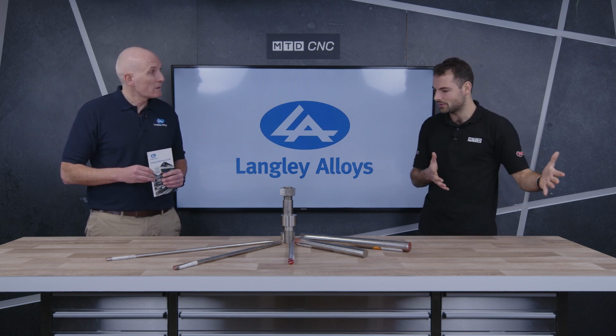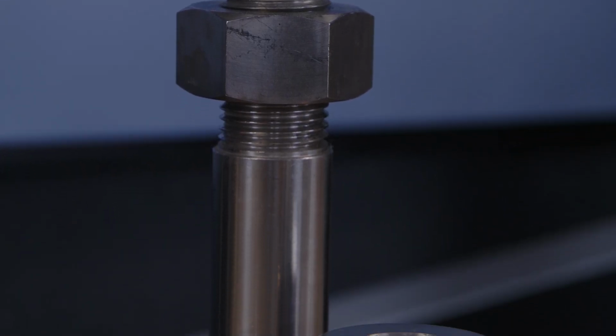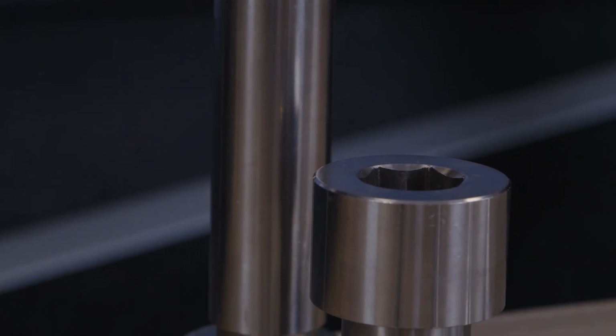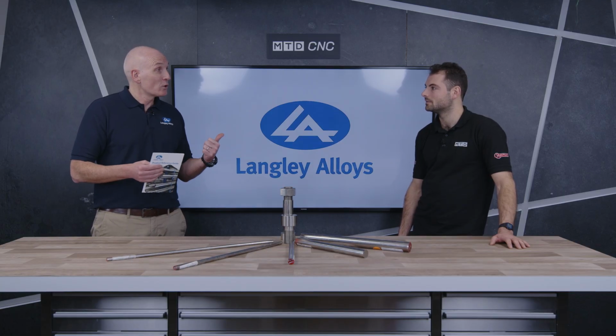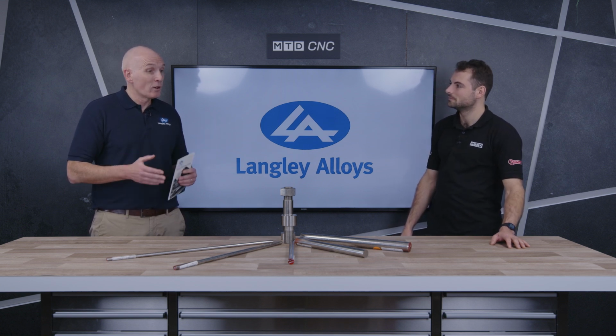Yep. But because of those properties, you can probably give a little summary. You brought some fasteners here, some small diameter parts. What are the applications of this grade? So, without going over too much old ground, it's a grade that's based on a 25% chrome content. That gives it great corrosion resistance. The combination of two different types of microstructure is why it's called duplex or super duplex, and that gives it great strength and great mechanical properties. And then its composition is carefully controlled so it achieves those properties without introducing too much cost. So you've got good strength, good corrosion resistance, good cost competitiveness, and so it will be used for lots and lots of applications.